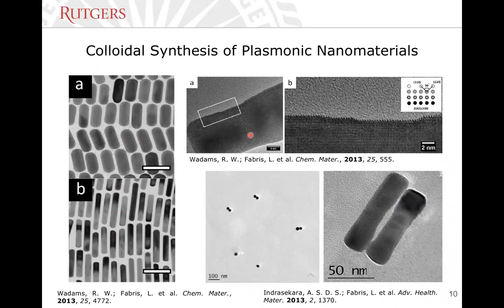And in particular, in this paper, we identified the growth mechanism and the evolution of their crystallographic structure over time that leads to thermodynamic stabilization of the particles. But we have also focused a lot on synthesizing nanoparticle assemblies, in particular nanoparticle dimers, both of spherical nanoparticles or of nanorods, because what we know is that the junction between these nanoparticles is where the highest field enhancement can occur. This is called a hotspot, the region around or nearby a nanoparticle where high field enhancements can be achieved.